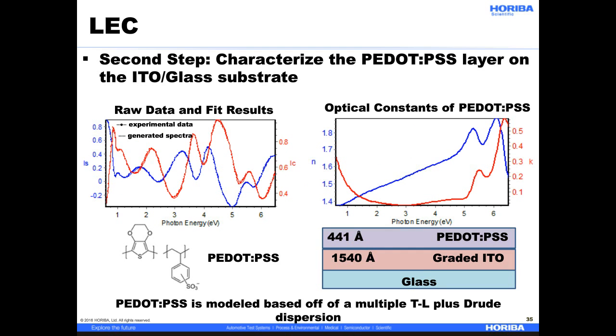The second step is to characterize the PEDOT-PSS layer on the ITO and glass substrate. The structure here, bottom right, is 441 angstroms from ellipsometry of PEDOT-PSS on 1540 angstroms of graded ITO on glass. On the left is the raw data, again from ellipsometry, and the fit results based off of the model that you see there.